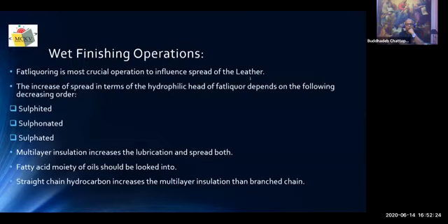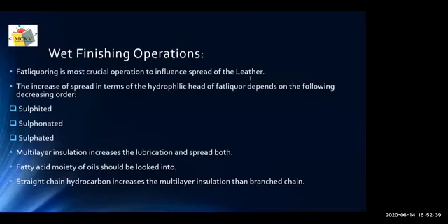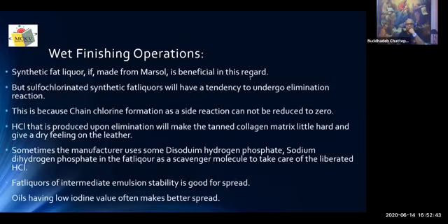The fatty acid moiety of the oil should be looked into. Straight chain hydrocarbon fatty acids increase the spread because multilayer insulation is more favorable than with branched chain hydrocarbons.